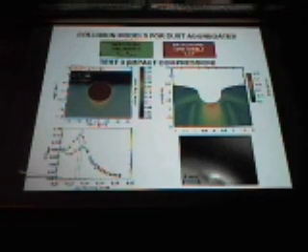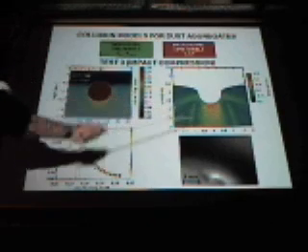What we see here is the volume filling factor, in terms of the sphere volume. So the main volume is compressed from 15% to roughly 23%, which is roughly here. And this is also what the model gives as a result.